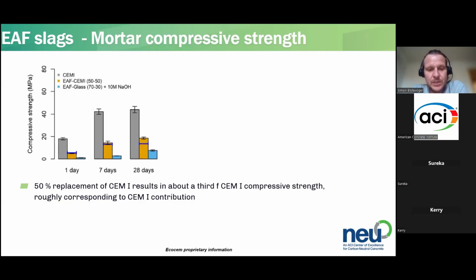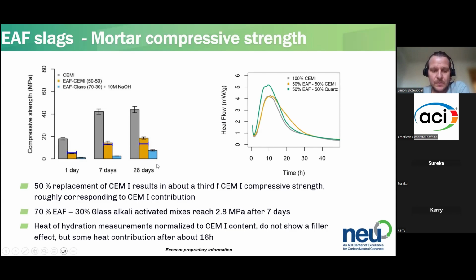As we have quite a bit of calcium in there, we tried around with alkali activation using sodium hydroxide, adding in some silicon. Basically nothing either. So the crystalline structure prevents hydration as it is.